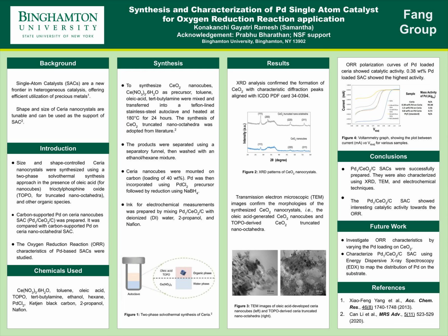Likewise, for synthesizing CeO2 truncated nanooctahedra, TOPO was used instead of oleic acid. The CeO2 nanocrystals were mounted on carbon with a loading of 40% by weight. Palladium was incorporated using palladium chloride precursors, followed by reduction using sodium borohydride.